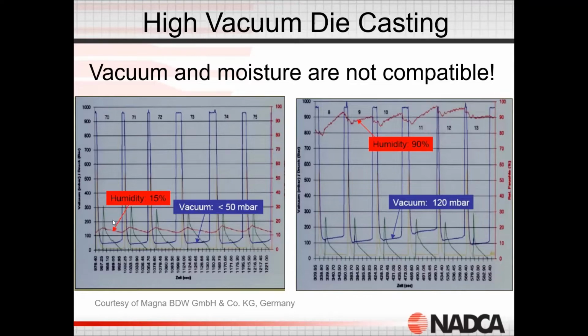And these humidity sensors are located at each vacuum point. Once again, a distinction between structural die casting and vacuum assist or normal die casting is that structural die casting can have multiple vacuum points. So we're going to have 2, 3, 4 vacuums inside of a mold, all drawing vacuum on the same mold, all measuring humidity. So we can see the humidity sensors at each one of the vacuum points, and then we can measure the vacuum level.